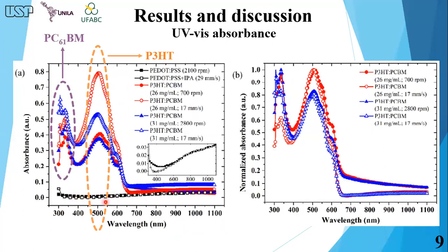PEDOT:PSS absorbance is lower than the semiconductor layer, which is desirable for exciton formation in the active layer and consequently to achieve high power conversion efficiency. Even better, PEDOT:PSS films made by blade coating show even lower absorption in the visible range.